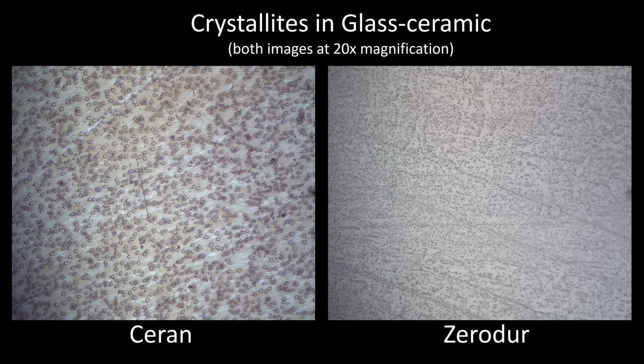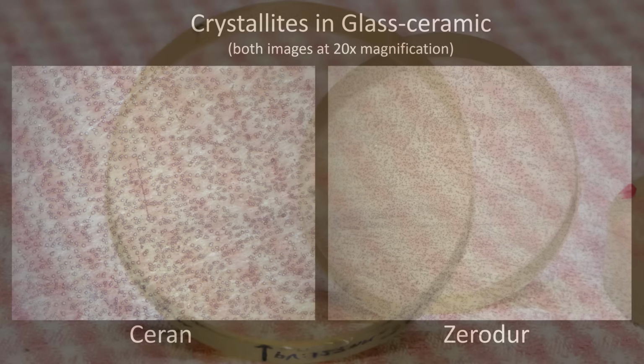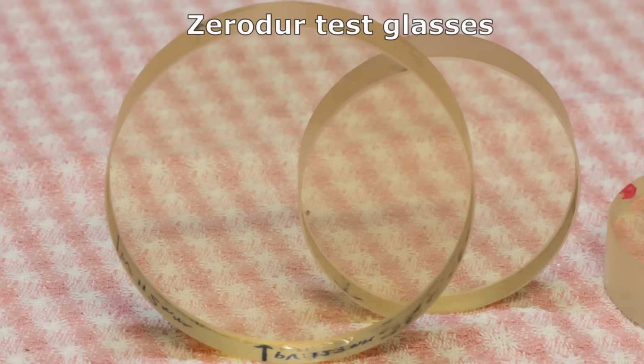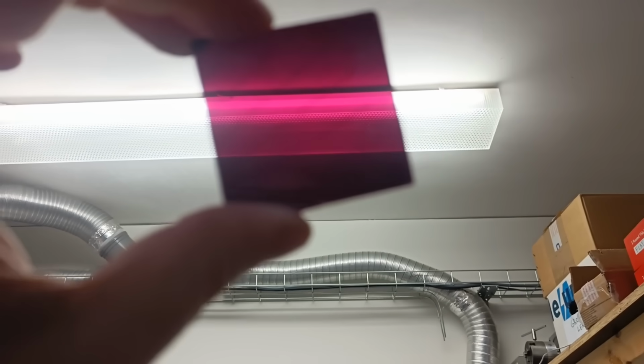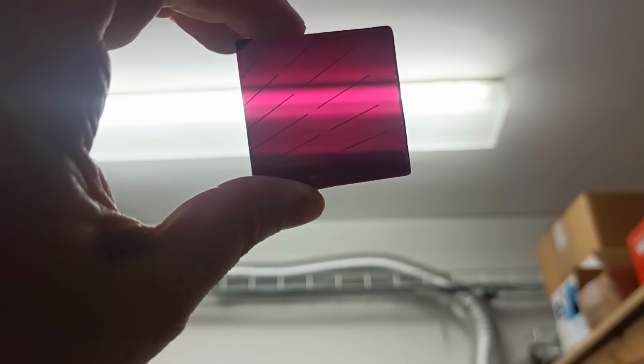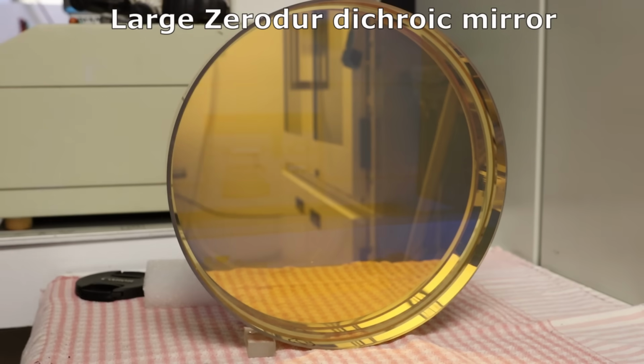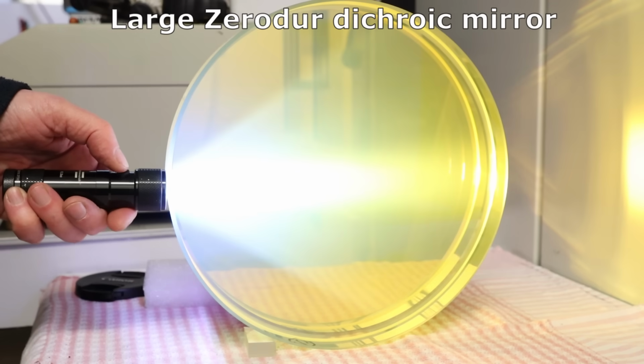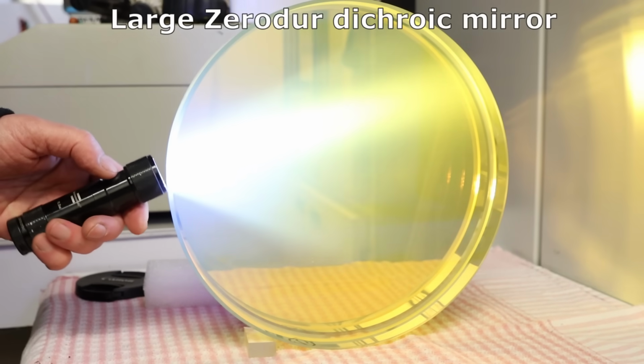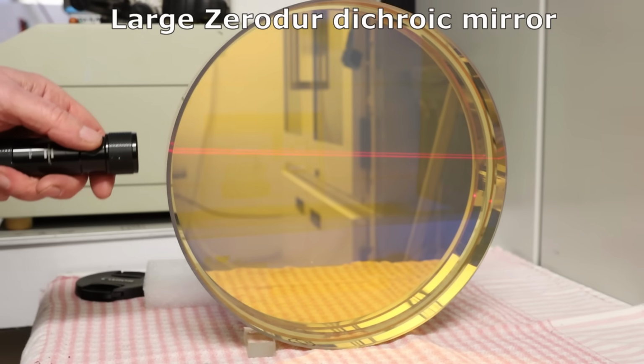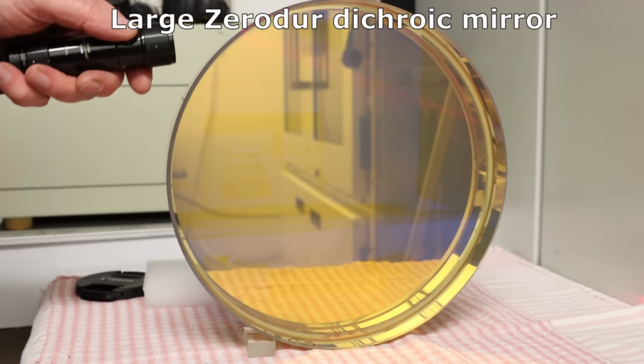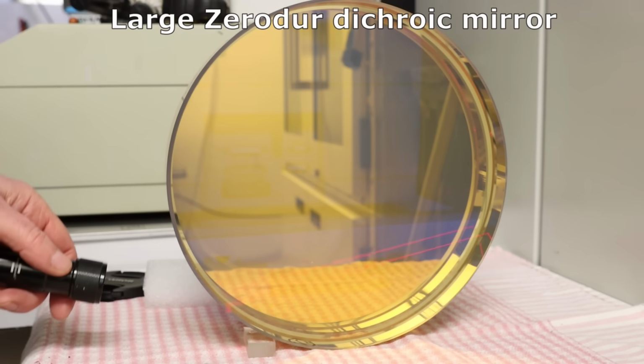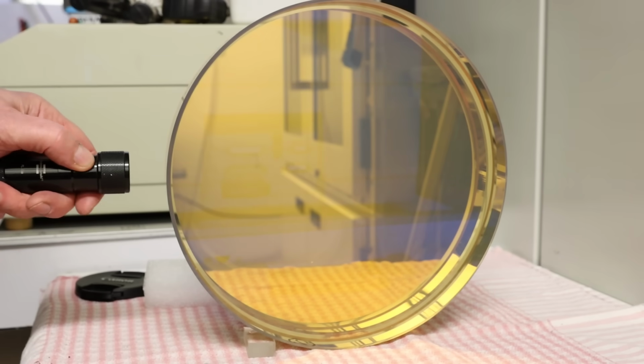Now I was kind of surprised by the size of the crystals in general, and that is because they don't really seem to cause a lot of light scattering. Zerodur is not intended for transmissive use, but it is actually quite transparent, and in the case of ceran, the dark color is actually due to an additive. And it's only when you use a high intensity light source like a very bright LED or a laser that you observe scattering in these materials. Anyway, both materials are far from opaque, and with crystals in the order of the wavelength of light or somewhat larger, I would have expected way more scattering.